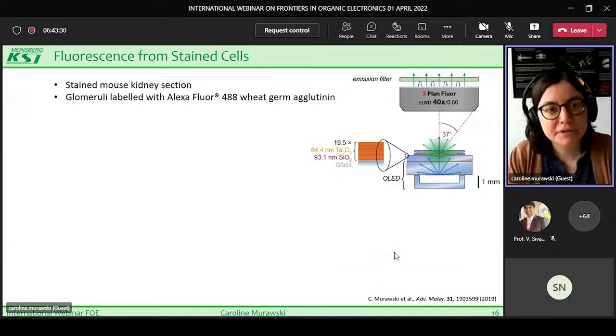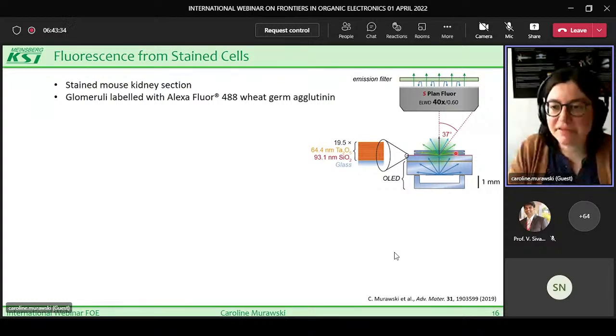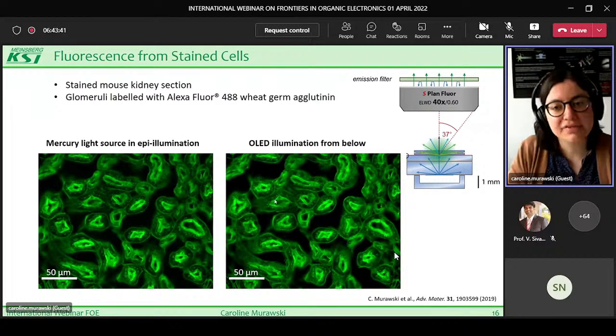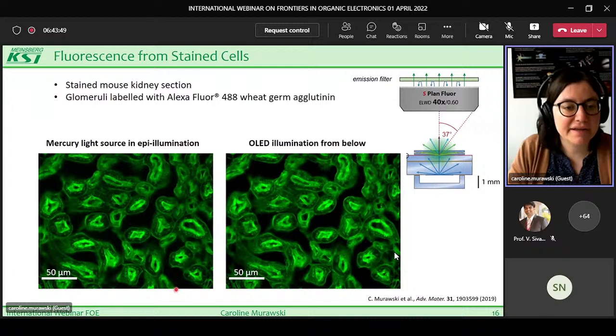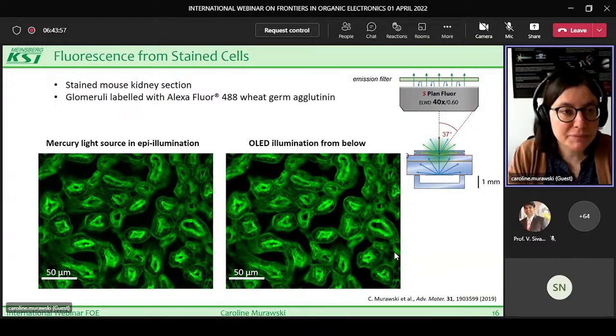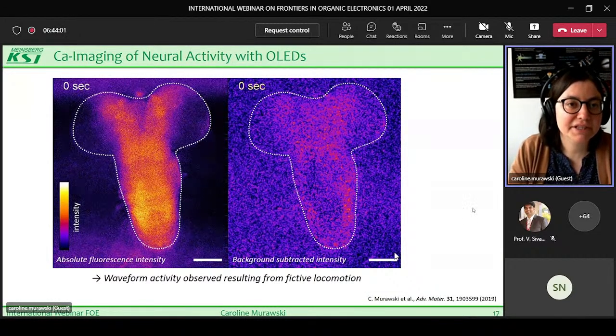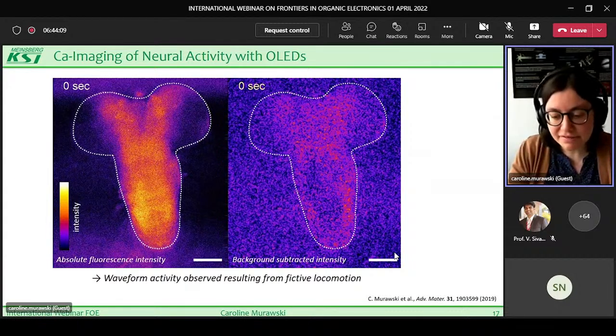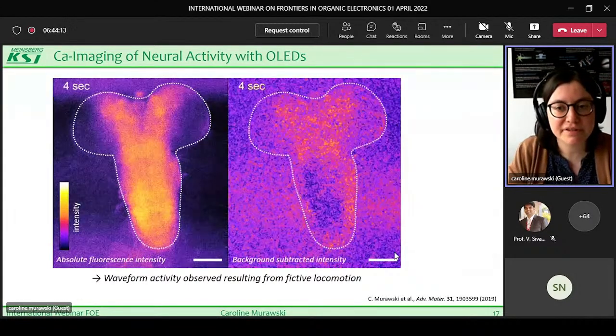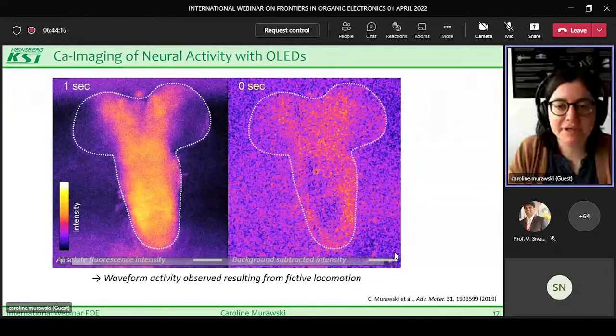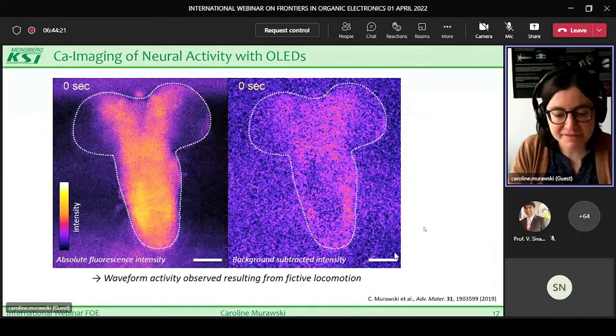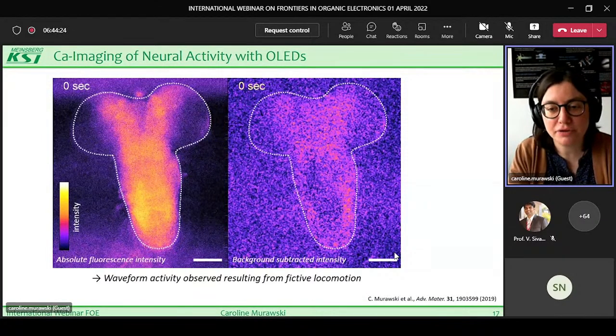But nevertheless, we used this device and put it underneath the microscope and stimulated different samples with it and looked at it here with the objective from the top. And as a result, we saw that we can basically achieve fluorescence imaging with the OLED at a similar quality as with conventional mercury light sources. And we also wanted to do neuronal imaging, and this is shown here. What you can see here is the central nervous system of a Drosophila fly, stimulated with an OLED light source, and we look at the emission of the fluorophore, and we could see such a waveform activity going on in the brain, which gives us basically a proof that we could successfully do calcium imaging using OLEDs.